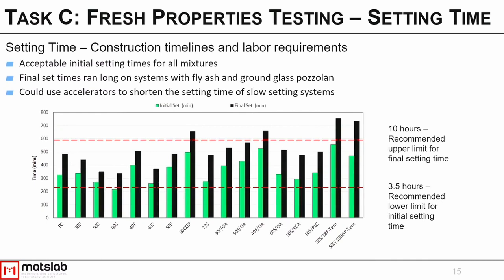For the most part, all of our mixtures were able to meet these requirements. Surprisingly, even our 77% slag was well within these requirements, especially with the final set time. And that had our highest amount of SCM, which typically slows down your setting. But this gives us a good idea of how much working time we'll have in the field and potentially how long it will take before we can strip molds and start doing other work on the concrete.